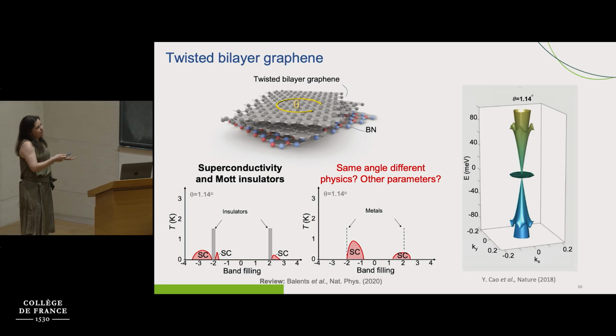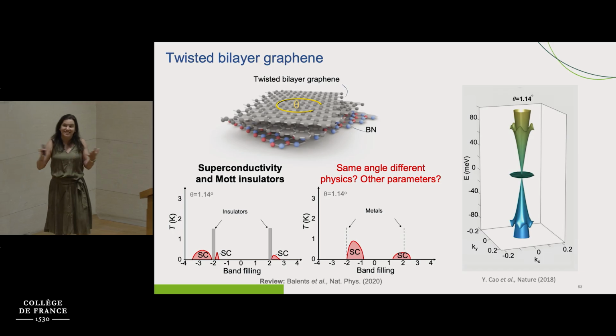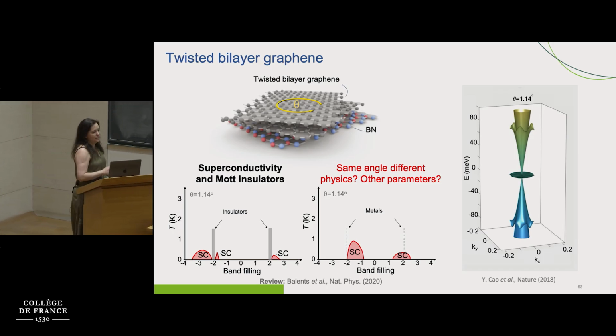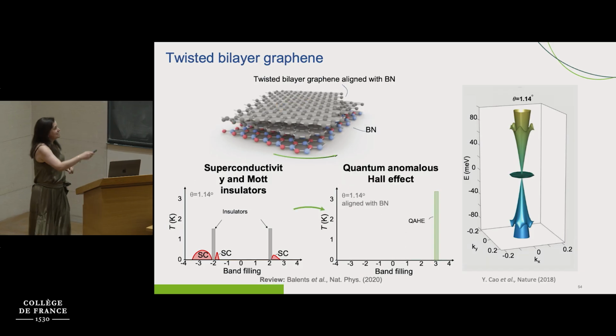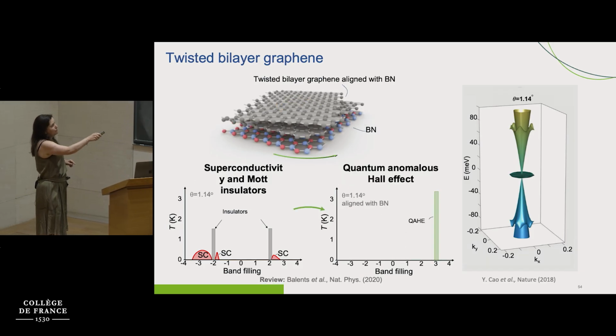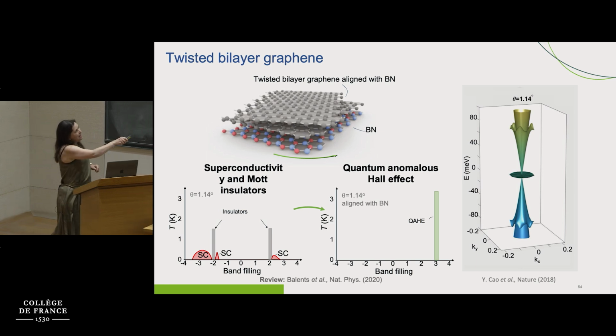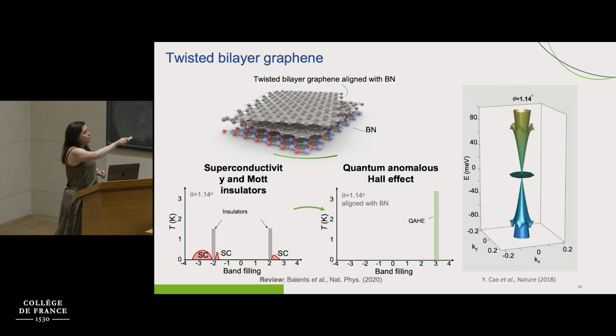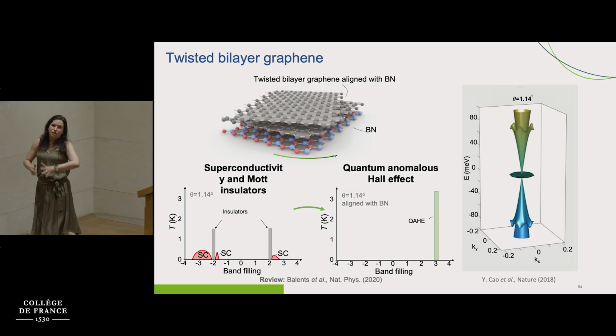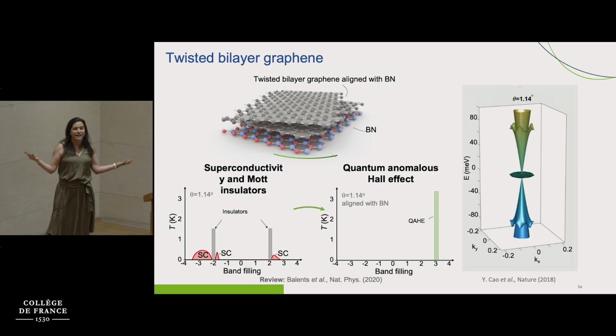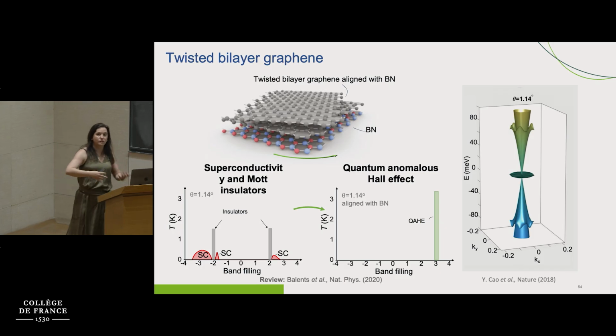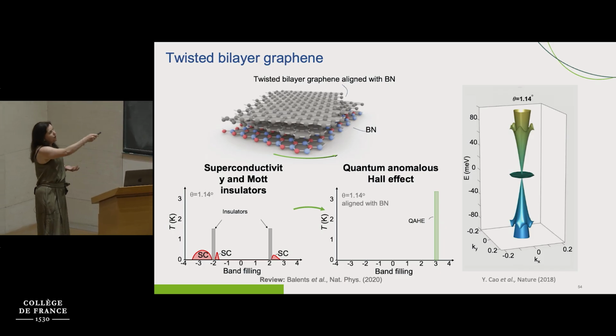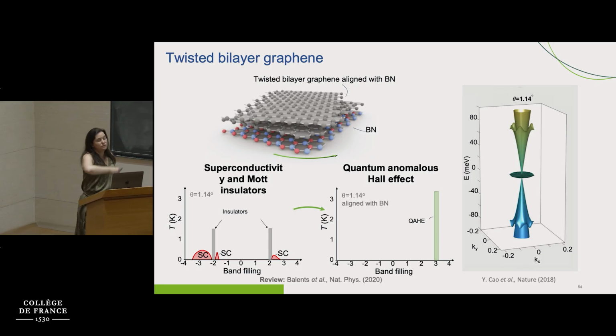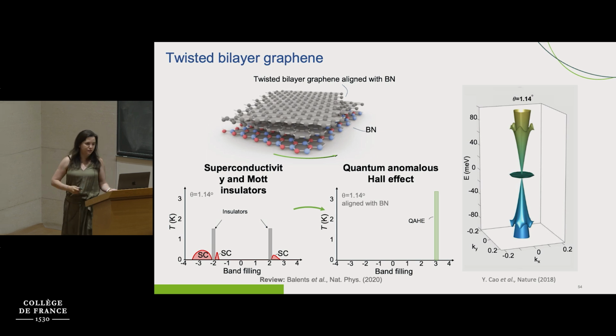So, okay, this is very interesting, but we are mostly concerned about topological states, and this is not, at least not that I know of, a topological state. However, if we take exactly the same system, twisted bilayer graphene aligned at the magic angle, and we also align the boron nitride that is the substrate, we are going to observe the quantum anomalous Hall effect. So why is this important? Remember that I just showed you, you can have 2 moirés and they might interfere with each other, they might lift new symmetries of the system. This is what's happening here. You have 1 moiré that is created by the twisted bilayer graphene, and a second moiré that is superimposed, created by the graphene and the boron nitride, okay?